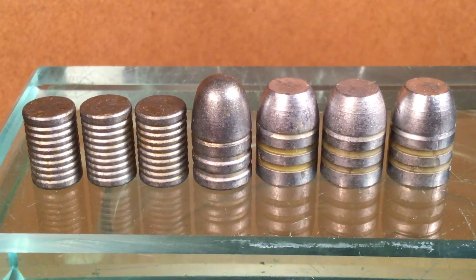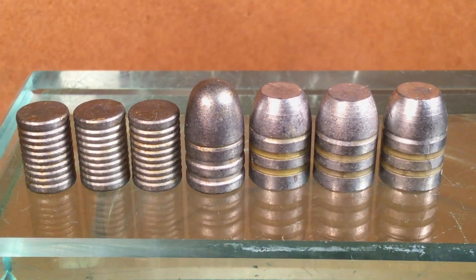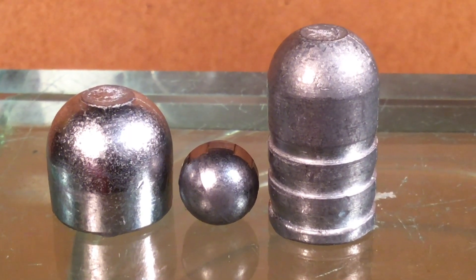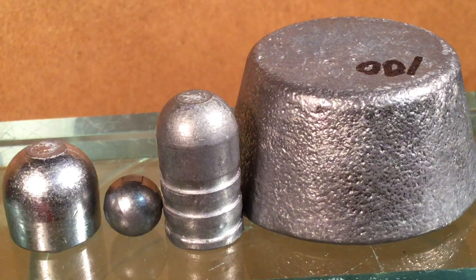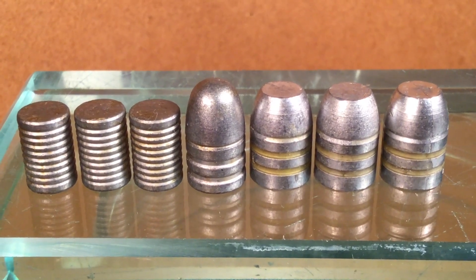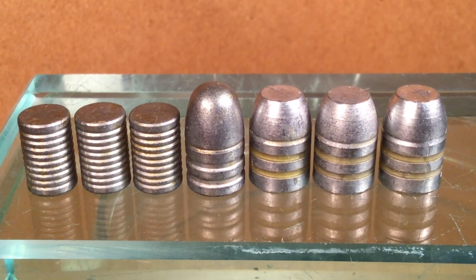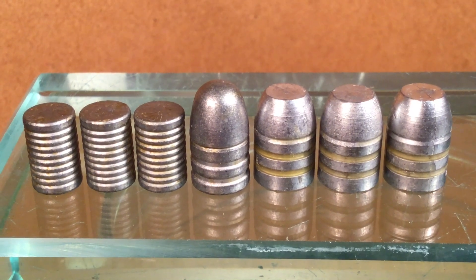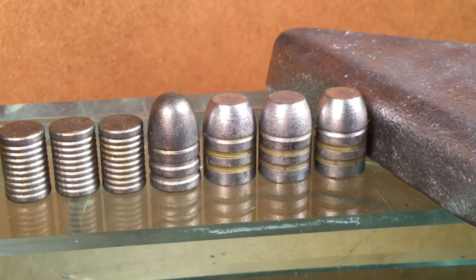The name of the game for many years was that bullet hardness should be optimized to the velocity or pressure we are shooting at. If we're shooting shotgun slugs or black powder projectiles, we want pure lead — BHN 5 to 8 depending on whose scale you're using. Moving on to smokeless powder: you see here are some bullets we shoot at standard velocity, which is around 750 to 800 feet per second. For standard velocity loadings — target or general shooting bullets — all we need is BHN 10 to 12, so plain range scrap works fine.